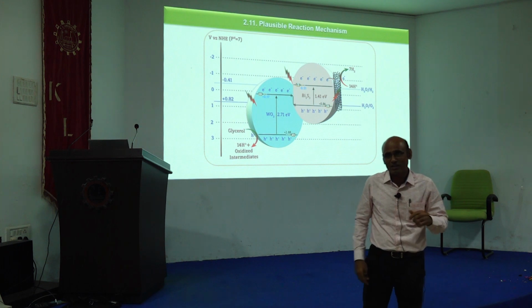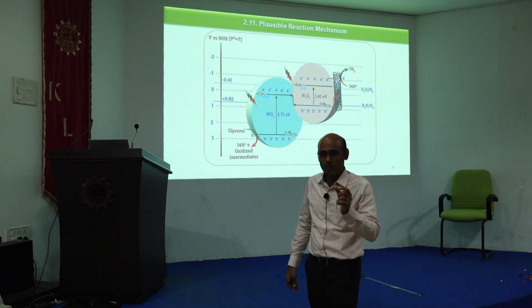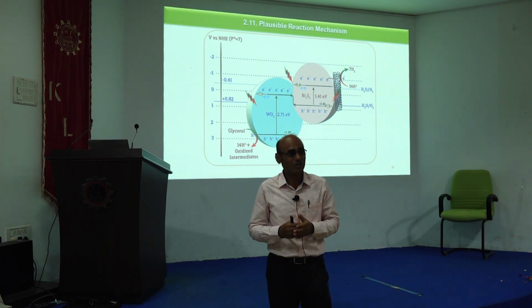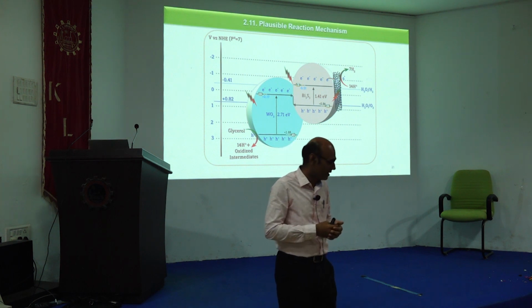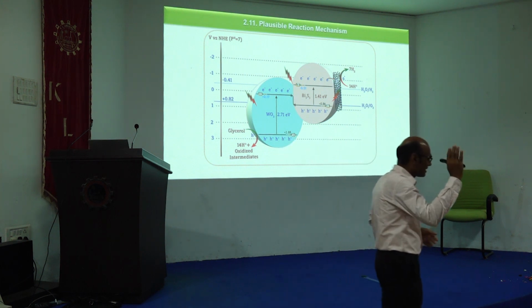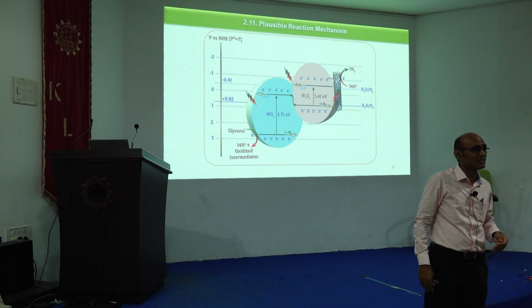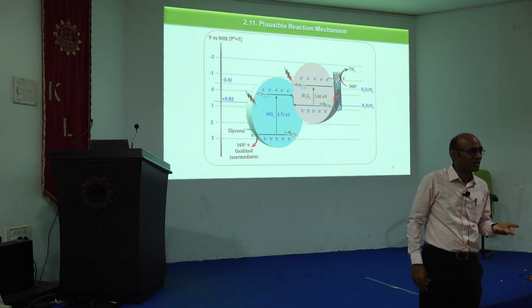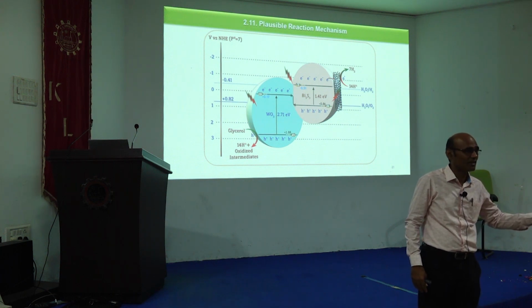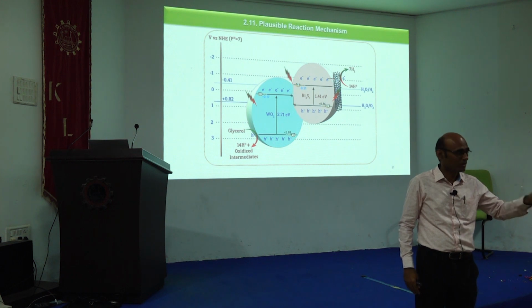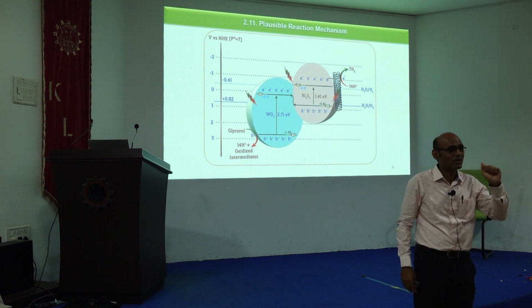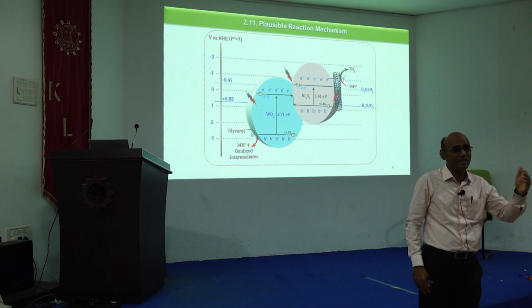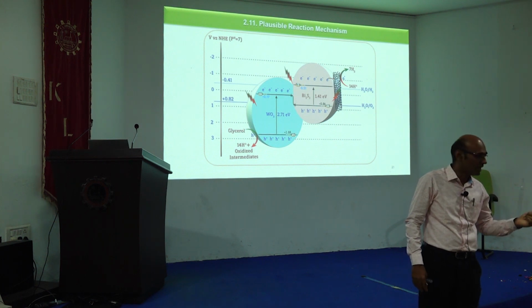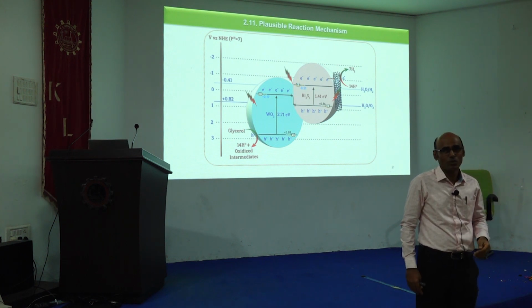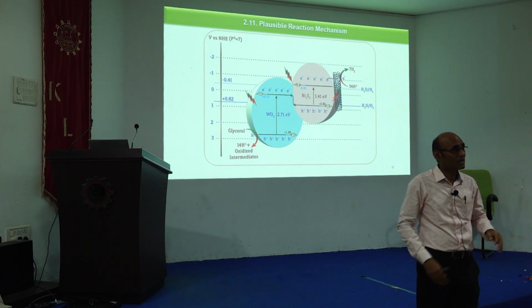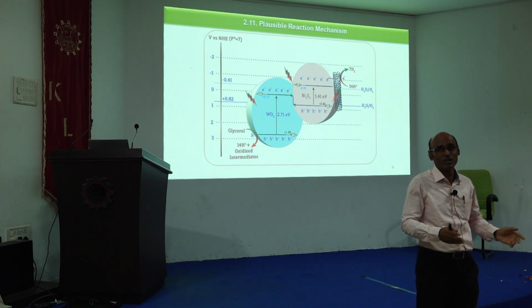Okay, and then when you are going for the prepared material, calcination is one step, heating at a high temperature. Calcination also we said, calcine at 400 degrees centigrade for 4 hours. How do we calcine? Calcination means you use a muffle furnace, right? You will go from room temperature to 400 degrees centigrade. How will it go? What is the rate of heating? Ramp, we call it. Either 1 degree or 2 degrees or 5 degrees. You might have used 5 degrees. Somebody will use 10 degrees. If you don't give anything...